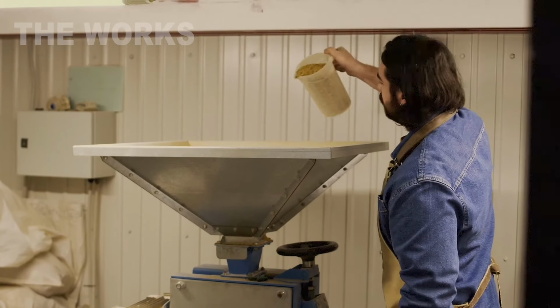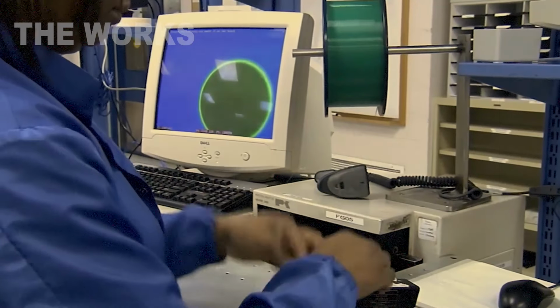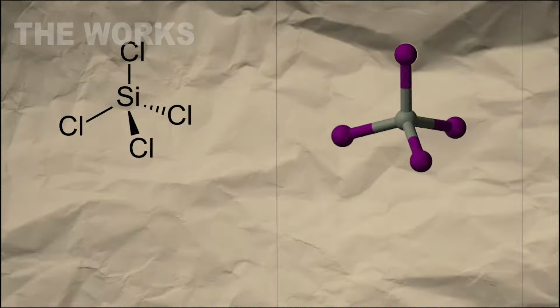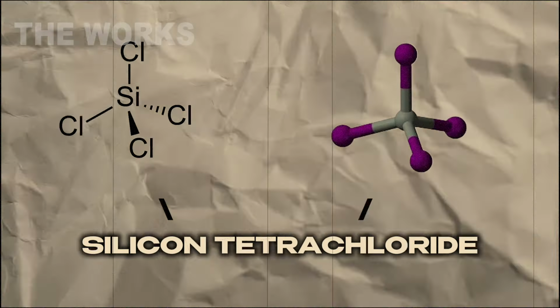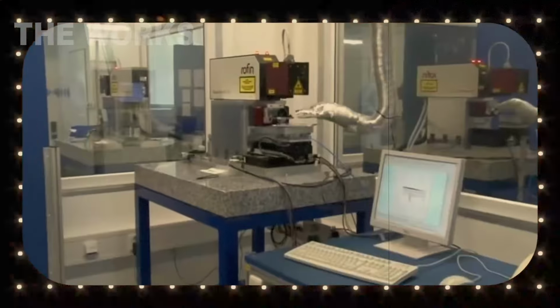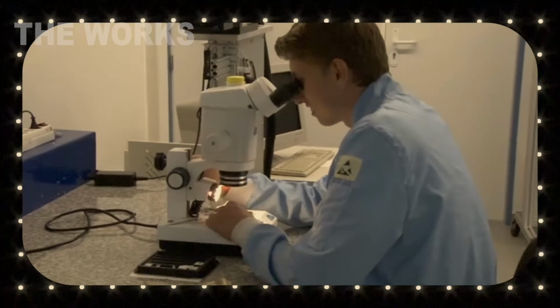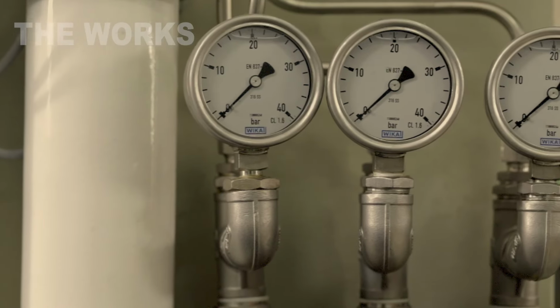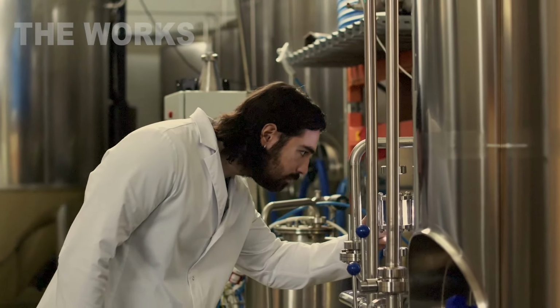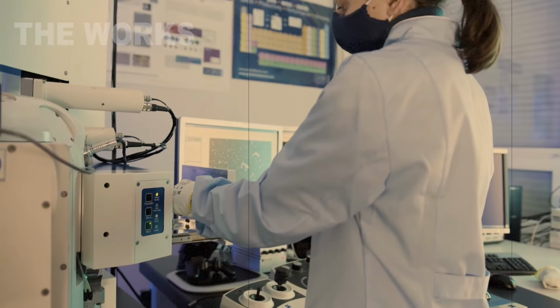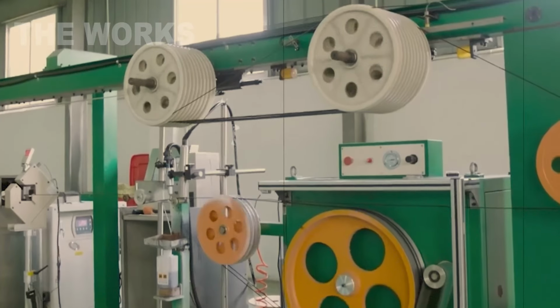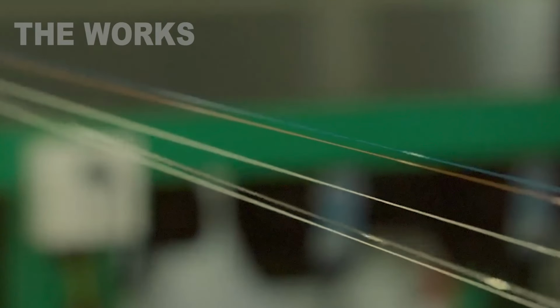Raw material for fiber optics isn't simply washed or filtered, it's purified at the molecular level. Manufacturers often employ gas chemistry. Quartz sand is converted into gaseous silicon tetrachloride, which is then distilled, filtered, and precipitated as the purest vapor. And only then is it converted back into glass. Add to this strict temperature control, humidity, and airflow in clean rooms, and you'll get an idea of how far removed this is from an ordinary sandy beach. Production laboratories resemble NASA's sterile zones more than a glass workshop. And all of this to ensure that every meter of future fiber contains not a single defect.